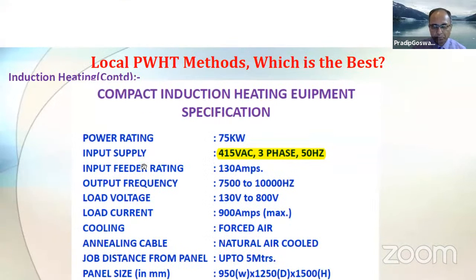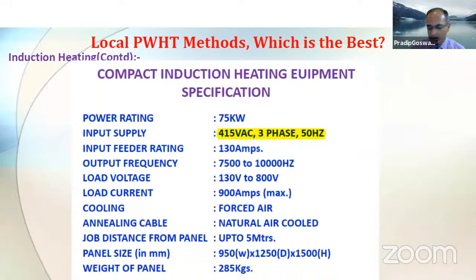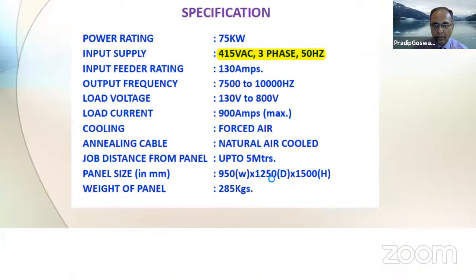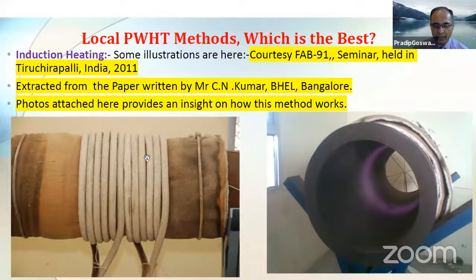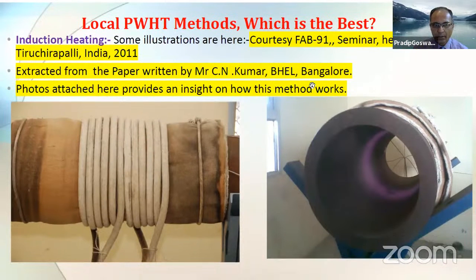Here is a typical local post-weld heat treatment method. This is typically the post-weld heat treatment cycle which is followed for this alloy. And as you can see here, this is a typical input supply for induction heating. And here is a demonstration of induction heating. I took these photos out of a paper which was presented by Mr. C.N. Kumar of BHEL Bangalore, in this Fab 91 seminar.